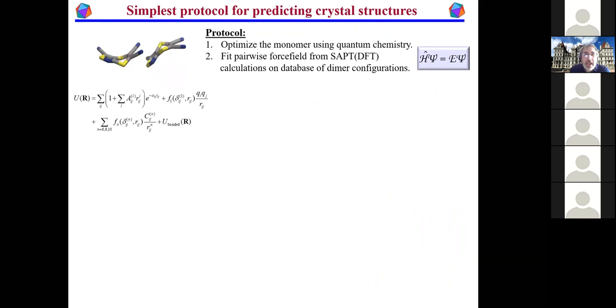Next, you have to create a force field, an interaction model. And this is actually very, very difficult, as it turns out, because often the energy difference between different polymorphs can be as low as a few kilojoules per mole. Very, very small. And so your force field has to be extremely accurate. And so in this case, what we did was we used SAPT-DFT. So you basically take your Kohn-Sham orbitals, and then you do perturbation theory on the real Hamiltonian. You do this on dimer configurations to create a pairwise potential.